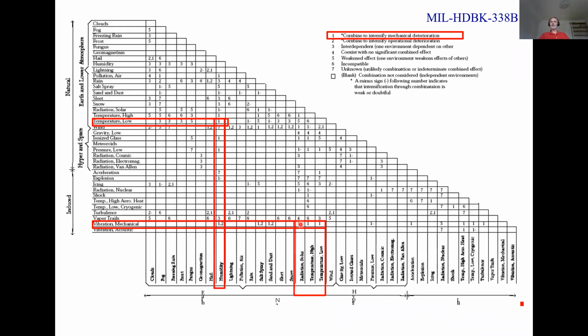So if you leave something plastic outside, like these small things which you put on the wire to hang your clothes to dry, and you keep them outside for a few years, then they become mechanically very, very weak because of the UV. So you have the combined effect of solar radiation, UV radiation, and mechanical vibration or mechanical bending. The same is true, of course, with high and low temperature. For high temperature, some materials behave too soft. Some materials, like plastics, become very brittle when the temperature goes below a certain temperature. So this is just a way that when you have this kind of tools, you can see what kind of combined effects there could be.